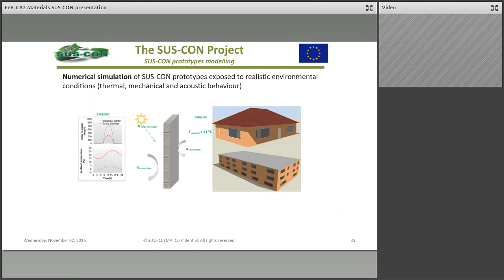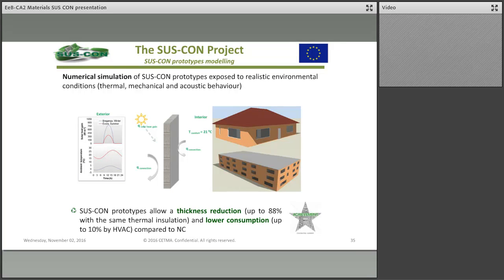We also performed numerical simulation of Suscon prototypes exposed to realistic environmental conditions, and we were able to conclude that Suscon prototypes allow a thickness reduction up to 88% with the same thermal insulation, and a lower consumption up to 10% compared to normal concrete.